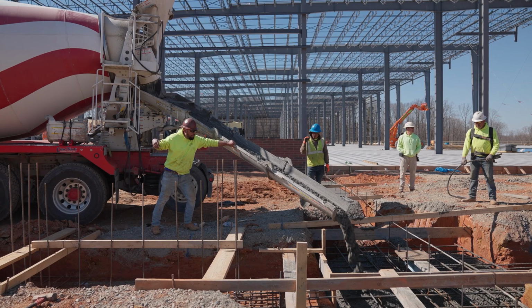Flash set, same deal. Concrete leaves the plant, 5, 6 inch slump, gets to the job site, it's a 3 or 4. You add water to it and the water's not doing anything to increase the slump. If you do it 2 or 3 times, you're gonna put 10, 15 gallons of water in and the concrete's still tight, low slump, we're probably going through a flash set phenomenon. If that's the case, my advice, send that concrete out. If it's on our end, we will replace it, no questions asked.